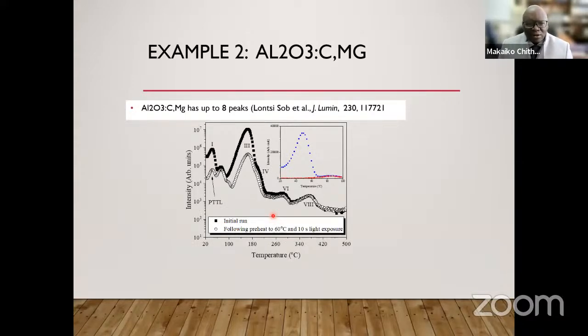This one is a little bit complex because it's got a huge number of peaks in its glow curve. This dark line here. Then this curve with open symbols is measured after preheating to 60 degrees and exposure to light for 10 seconds. So the preheating removes the first peak, and a 10 seconds light exposure regenerates the first peak. So it's an example from aluminum oxide.